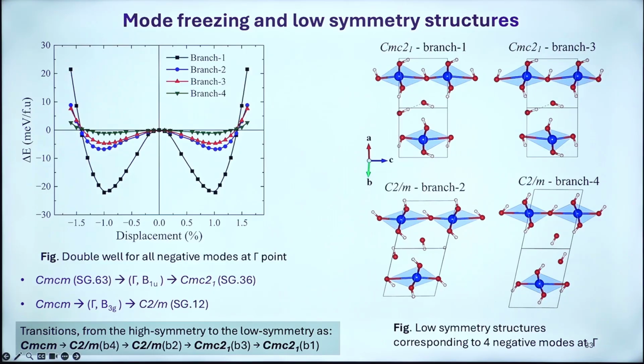So what I am trying to say is, I freeze the phonon mode, and then I say there is some structural transformation happening, for example here a paraelectric to ferroelectric transformation. I take that particular branch and see which are IR active and which are Raman active. Then I displace and get the total energy for each branch, branch 1, 2, 3, 4, and map it to the crystal structure.